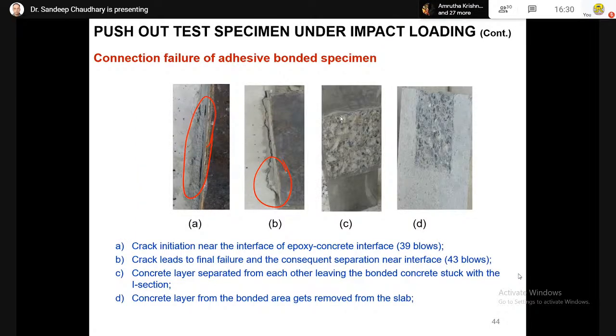So if you see the connection failure in case of adhesive bonded specimen, what we observed was initially there was a crack initiation near the epoxy concrete interface, typically for that particular case which you observed, say for 39 blows. So there was a crack initiation. That crack led to final failure and consequent separation near interface after 43 blows. So within 4 blows, there was a final failure. And the concrete layer separated from each other. That means the bonded concrete was still stuck with the I-section. So as such, the epoxy itself did not fail. The failure was within the concrete itself. And then concrete layer from the bonded area gets removed from the slab with time.